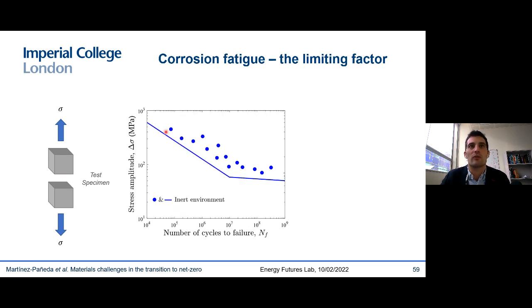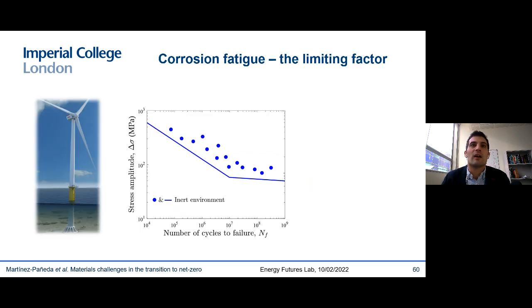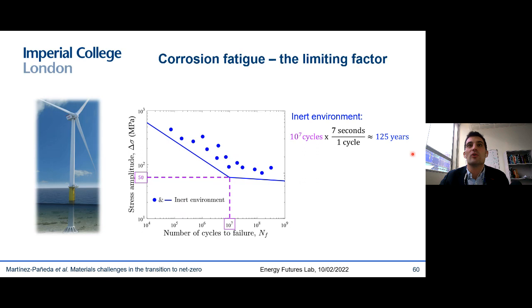And you draw it, of course, in a conservative manner. And then you go to your wind turbine monopile, and then you see what are the relevant loading conditions to your structure, and therefore take the relevant stress amplitude, go into this graph, and determine how many cycles will occur before the failure of your component. And since you know the loading frequency at which this wind turbine is being subjected, then you can figure out the amount of time that it will take before it fails. And this gives you this number, for example, right? 125 years.